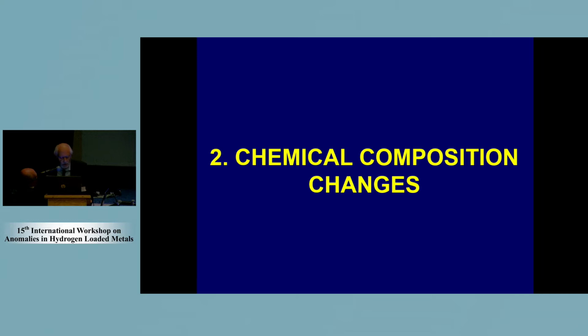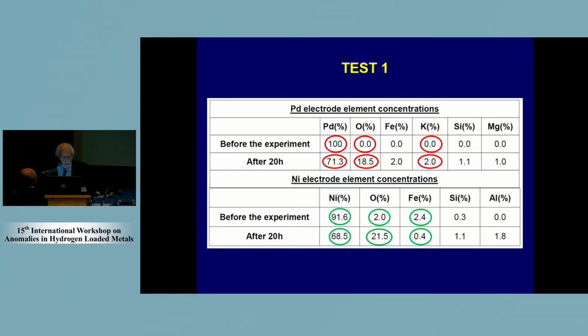Then we have section 2 about chemistry, very interesting, very important in my opinion, just to understand what is going on. I have to say that we used the best specialists in Politecnico di Torino for many years, and they used the EDS technique. It means energy dispersive spectroscopy or X-ray spectroscopy. In the first test, test 1, we report only the situation at the beginning, before the test, and at the end, after 20 hours. You see the palladium, you see the particular values, which I intend to comment more.